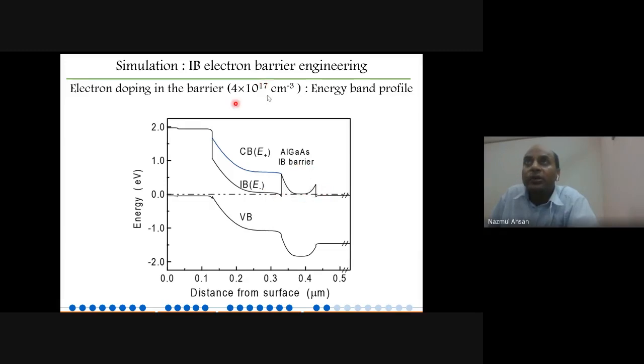To avoid that, you reduce the doping concentration in the barrier by one order. Now the width is so long that the electron says, oh my God, this barrier is too deep, so let me wait here for the second photon, then let me go higher. This is how we design the doping profile. With even less doping, the electron says, this is too thick, so let me wait right here for the two-photon absorption. So if you have a low electron concentration in your barrier, that can stop the electron tunneling and improve the two-photon absorption. This is how we design the device.